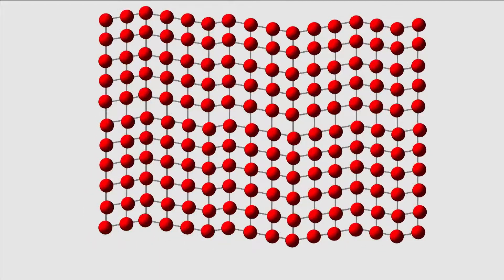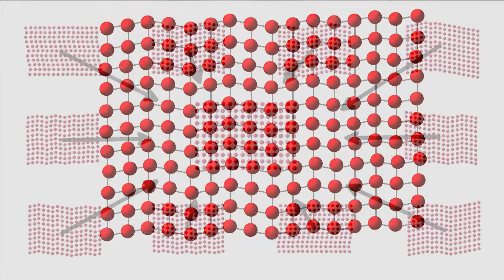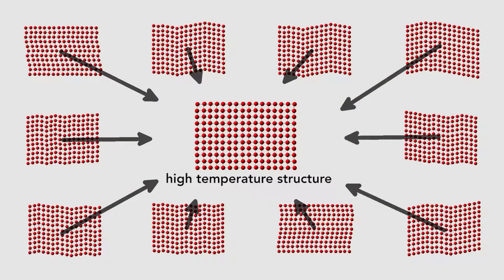So when the temperature is raised again, these rhombuses, no matter how they are distributed, return to tidy squares. The only structure that can result is the original structure, and so the nitinol reverts to the shape it had at high temperature.